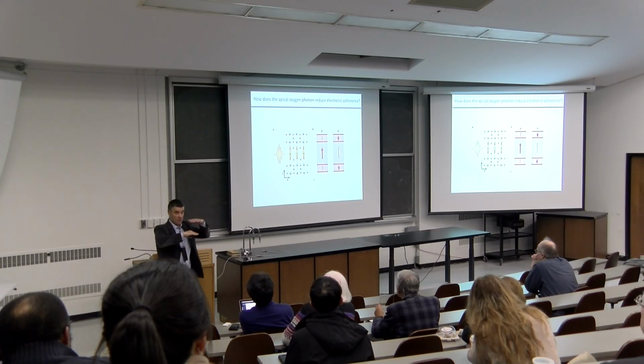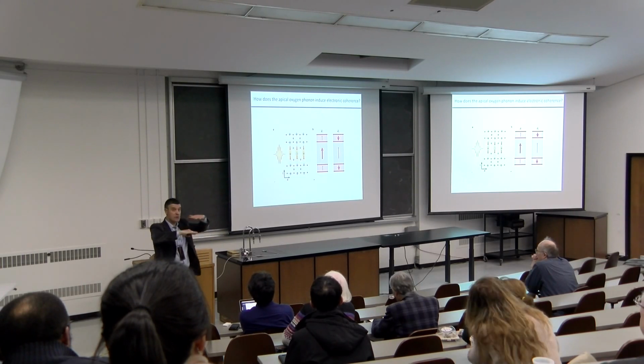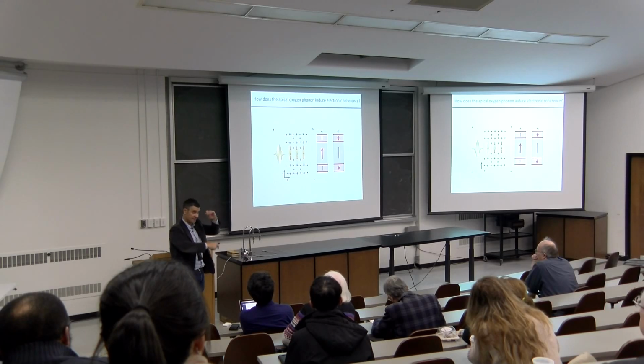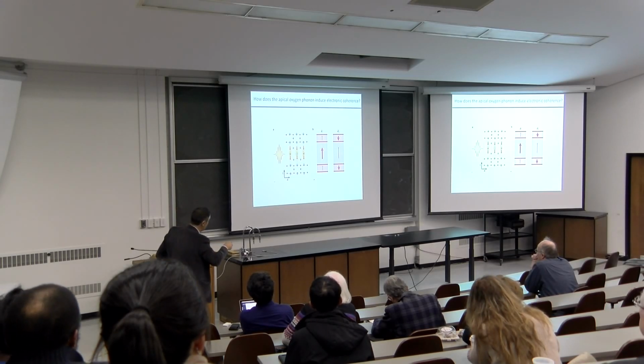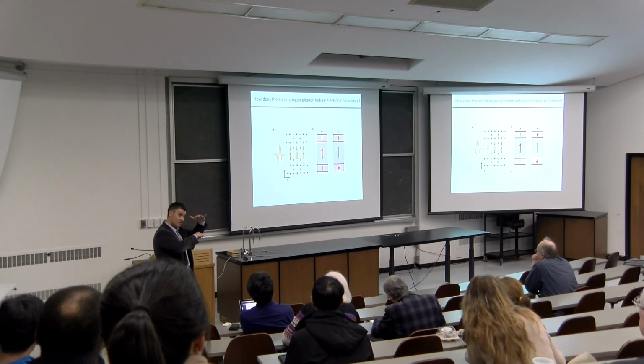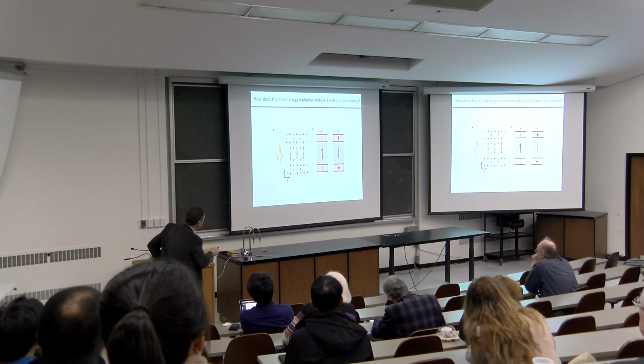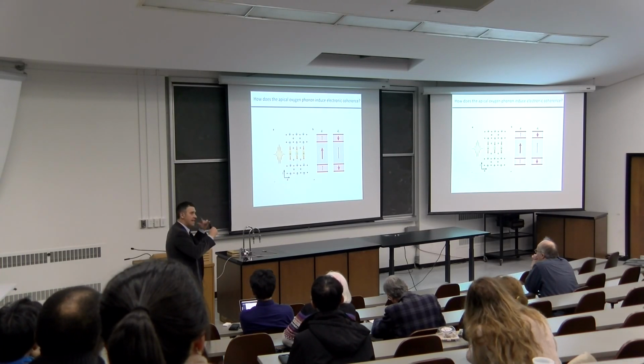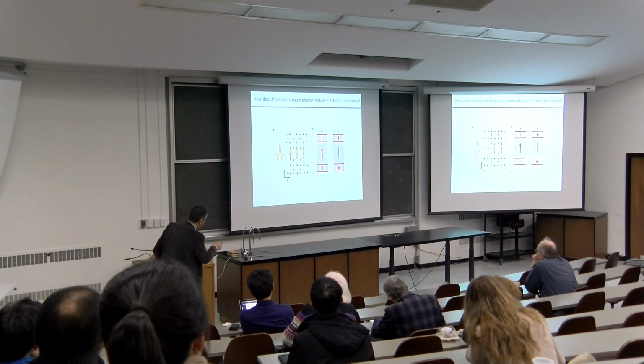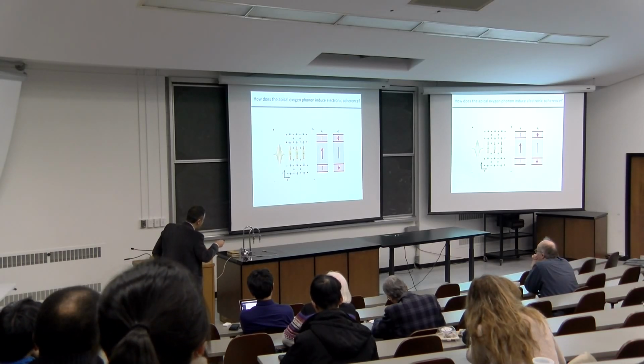So basically, one word. Cuprates host superconductivity within the planes, and then these planes are coupled by the Josephson effect, basically. So one has different tunneling modes, and normally one has only one frequency, but because these are bilayers, one really has two tunneling modes. One has a tunneling mode between the bilayers and within the bilayers.